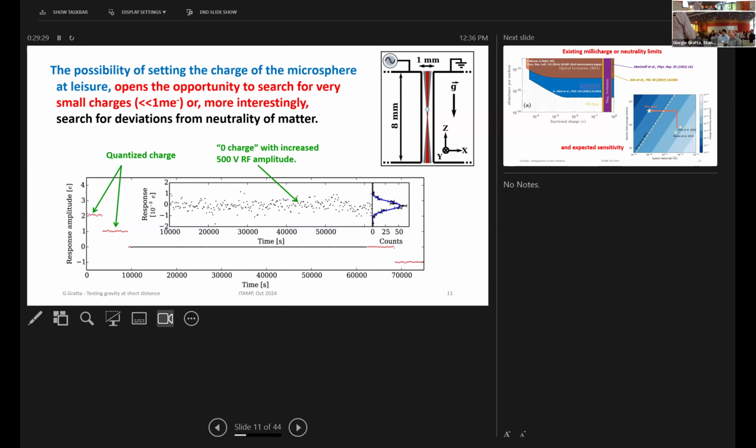But we've taken a lump of those things and put them in an electron microscope, and if you actually fit circles to those things for that ensemble, whatever that is, they're all within 1% from being spherical. Okay. But you must have to average over the non-spherical nature of them somehow. There are also some that are defective, and you can see them in the microscope, they're like half spheres, and those you can't even trap. We suspect that those are the ones that just fall off.